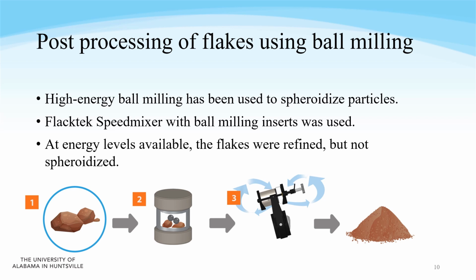In an attempt to do this, we used ball milling. Now, high energy ball milling absolutely does spheroidize particles. It partially melts them so that they reform and they're round when they come out. However, we did not have a high energy ball mill. What we had was a speed mixer on loan from Flak Tech with ball milling inserts, so not quite as fancy, not quite as high tech. And at the energy levels we had, we were able to refine the flakes, but they didn't melt at all, so they didn't spheroidize.